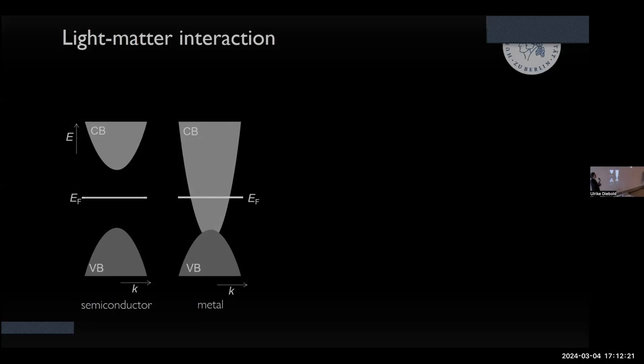Okay, so when it comes to photoexcitation of matter, there are various processes that are important, in particular when you look at the ultrafast timescale. Here I'm comparing photoexcitation of a semiconductor and a metal. Obviously, you all know that the semiconductor has the Fermi energy in the gap. The metal has a conduction band that is partially filled. Then we photoexcite the semiconductor. We create holes in the valence band, electrons in the conduction band. And then in most semiconductors, after relaxation to the band edges, they form excitons, bound electron-hole pairs, and they have a binding energy that is determined by the dielectric function of the material.